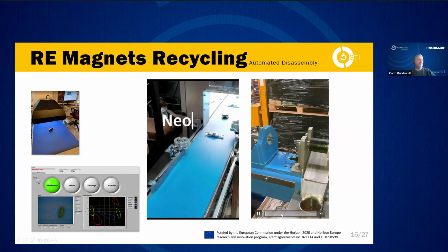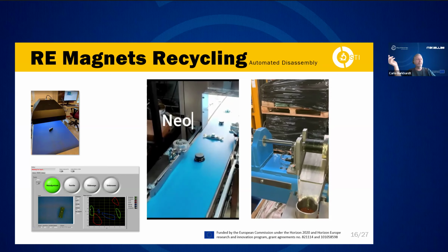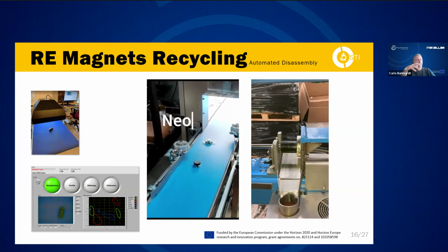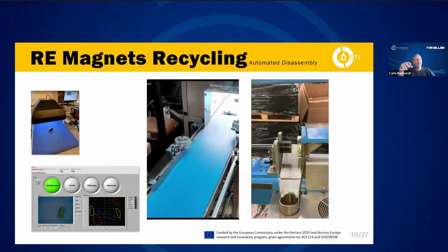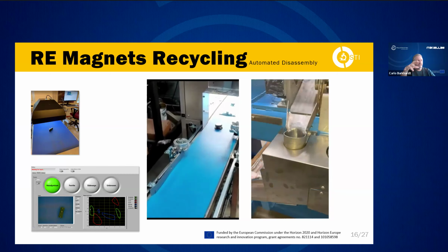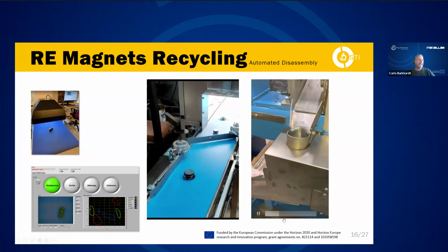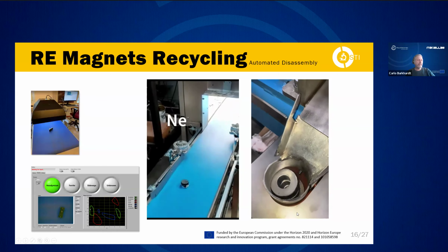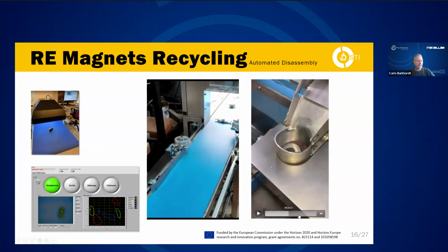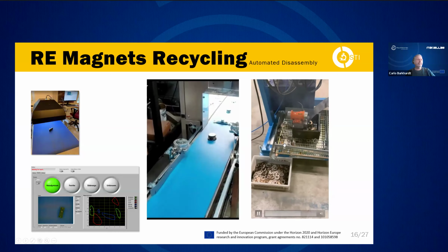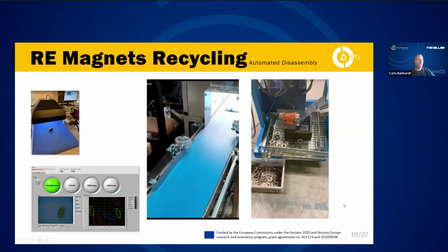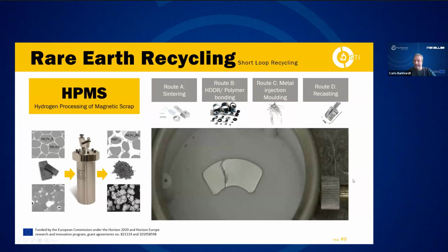A third thing we are playing on with is, of course, motors with embedded magnets. You see here a machine that presses out the shafts. That's then doing a heat treatment of the rotor that's falling down, and then is separating, let's move a bit quicker here, the magnets from the electrosheets. All these things are IP protected, as is this hydrogen processing of magnetic scrap that Sorana has shown before, which is when you introduce hydrogen into the system.